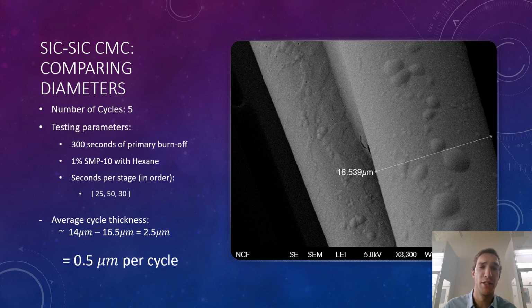And then again, as I mentioned, we're going to compare the diameter so we can get an initial thought as to what the average deposition per cycle is on this. Here, this is the 5 cycle image of 300 seconds primary burn-off. The average diameter from the spec sheet is 14 microns, and then comparing that to the 16.5 microns, we're looking at 2.5 microns total buildup for 5 cycles, which comes out to roughly half a micron per cycle. This is again just an initial estimate. We will be doing further investigations into a more accurate per cycle buildup.